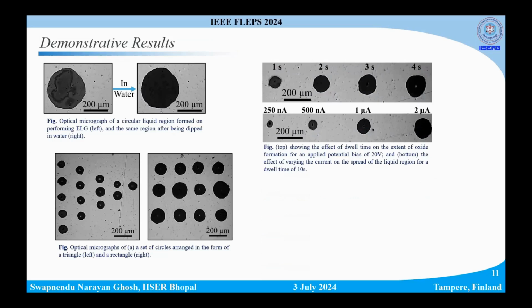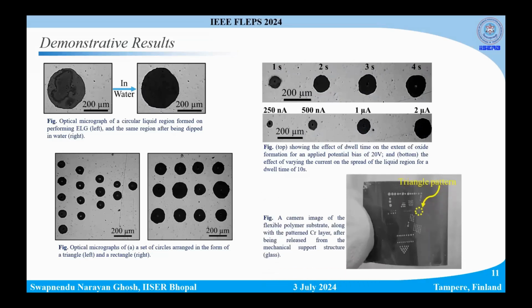And this is the effect of applying a constant current instead of a constant voltage, because the oxidation process is an electrochemical process. So this shows the effect of constant current, and this is a camera image of the Kapton substrate after the mechanical support layer was removed.